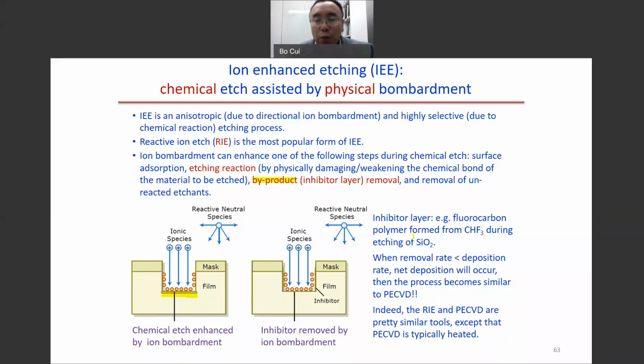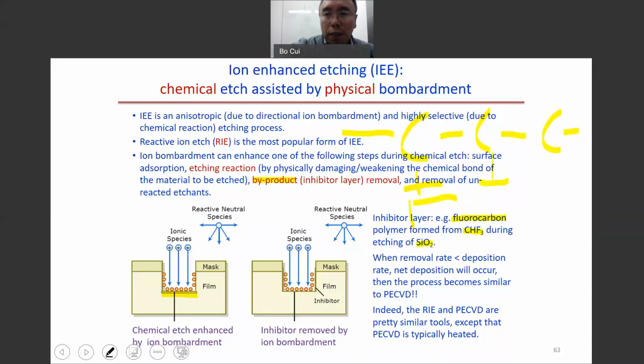For the etching, for example, we use CHF3 gas to etch silicon dioxide. This gas will form a fluorocarbon polymer, something like this. You have the carbon, and fluorine here. So this is the fluorocarbon polymer. This polymer will be coated on the side wall as well as on the bottom of the pattern. The fluorocarbon polymer on the bottom will be removed by the bombardment, but the fluorocarbon on the side wall will be less removed. This way, it can give you anisotropic etching. It can also help to remove the unreacted agent.